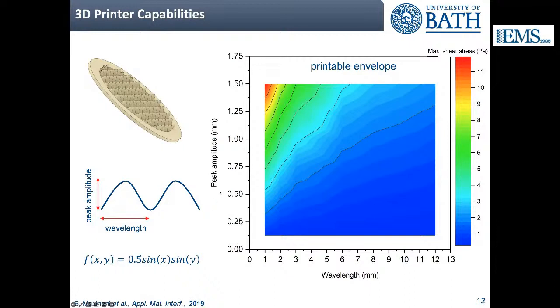So what you get when you make a map of the peak amplitude versus the wavelength, you can calculate the shear stress, which is given here in these different colors in this 2D plot. The shear stress you have at the surface of the membrane. You want the highest possible shear because that means there's more force acting to dislodge fouling. So in principle, you would like to use a very high peak and very short wavelength, so something very pointy and very close to each other.